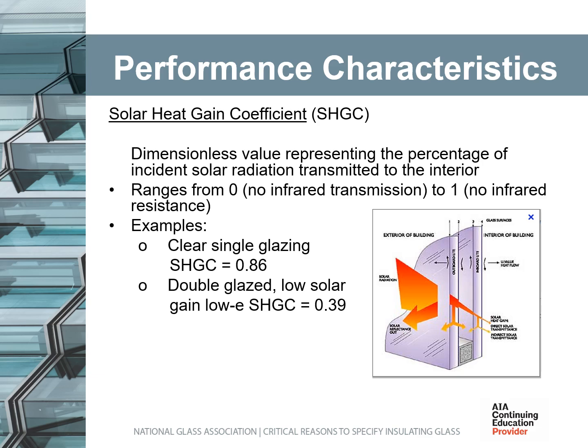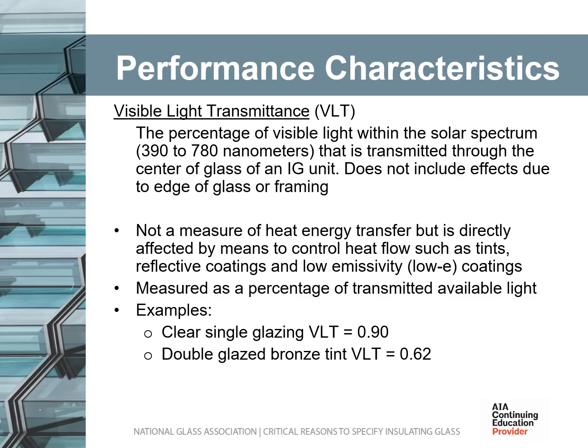Some examples would be a double-glazed IG with low E coatings blocking a lot of the infrared transmission having an SHGC of 0.39, while a clear single light of glass has around a 0.86 SHGC. In some climates, a higher SHGC is desired to help heat a space, but it's a delicate balance in most locations. If the SHGC is high to help heat in the winter, it could be a problem with overheating in the summer. Visible light transmittance, or VLT, is the amount of light in the visible portion of the spectrum, 390 to 780 nanometers, that passes through a glazing material. A higher VLT means there is more daylight in a space.